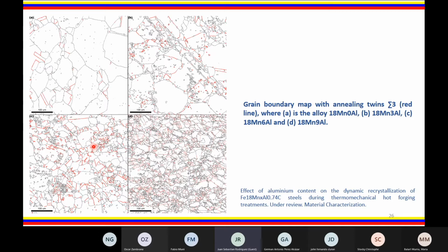In this case, it is observed that the variation in aluminum increases the area fraction of the twins, which is directly related to the increase in dynamic recrystallization. The explanation for the refinement of the microstructure through thermomechanical treatment is based on the following hypothesis. It is very likely that the lower aluminum content favors the rapid generation of differences in dislocation densities between different regions, which generates many sites of recrystallization of the grains. And by continuing the thermomechanical process, the previously formed grains grow at the expense of others, consuming the density of remaining dislocations, leading to a growth of grain size.